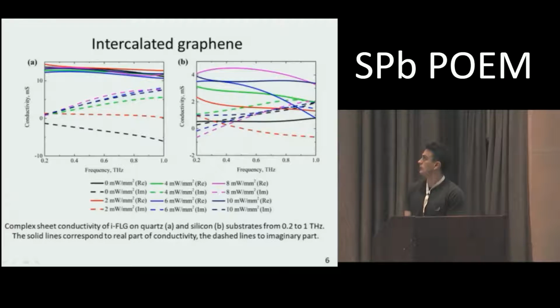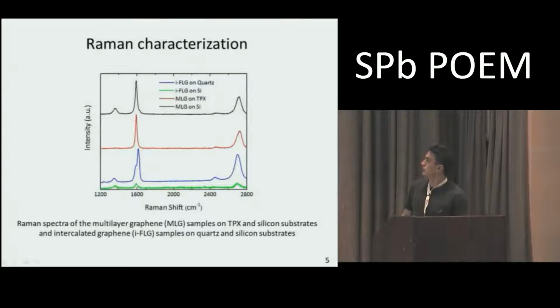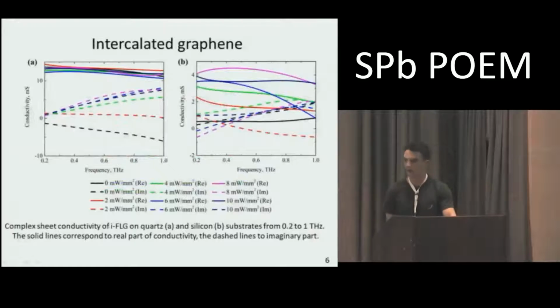For the second sample on semiconductor substrate, there are changes both in real and imaginary parts of conductivity, but the values of the conductivity are low in comparison with the previous sample, which can be associated with the low quality of the sample. It's well shown on the Raman spectra. It's the green curve, so these are not very reliable results for the chemically modified graphene on silicon substrate.